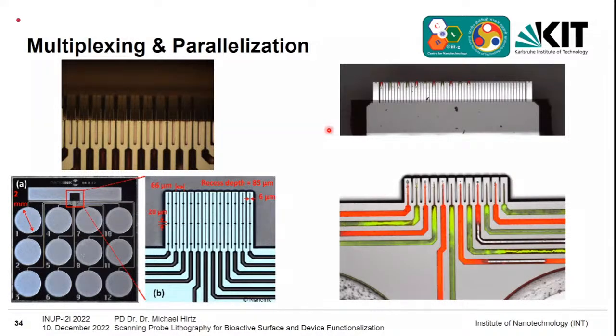What's also a nice feature of DPN is that if you go for parallelization, you can also do so-called multiplexing. For this, we use microfluidic so-called ink wells that you can fill with the desired ink by a pipette. You see it's still 2 millimeters, so that's addressable by hand by a pipette. And then there are microfluidic channels that take ink from here to a place that lines up with the separation of your tip array. And then you can dip your tips in parallel into these small containers.